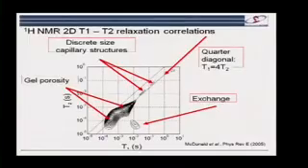So this would support the idea that these little nanocrystalline regions are actually joined together in the same way you have in a polymer structure. Those of you who have studied polymer structures, the structure of semicrystalline polymers, will be familiar with this idea of regions where the polymer chains are well organized and then the polymer chains go to another region. So this is really the big controversy which is still not resolved about CSH.